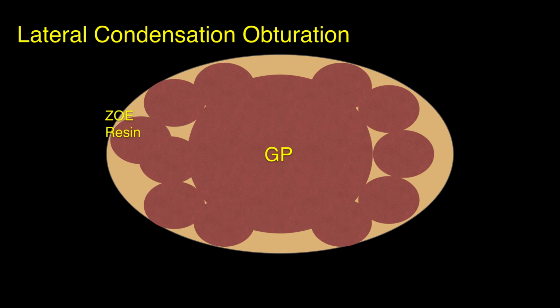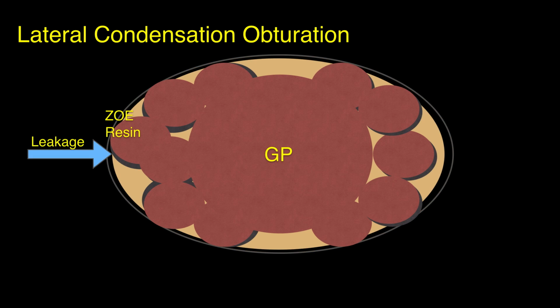So what we decided to do is to go and say, well, let's try to fill the oval areas with more of these lateral cones, which caused us to have a lateral condensation technique. We developed the lateral condensation technique to address that particular issue. Predictably, again, the same problem arose where you had shrinkage of the zinc oxide eugenol based sealer around these little mini cones, which actually may have in fact increased leakage at various different interfaces.